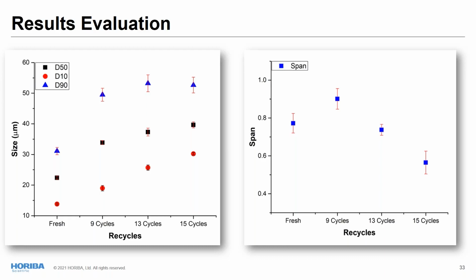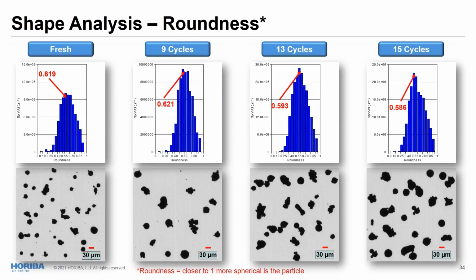It can be a good thing if, let's say, you're making a pharmaceutical ingredient or any other chemical where you want to control the speed of the chemical reaction. Of course, the narrower the particle size distribution, the more homogeneous the reaction is going to be. This is exactly what happens with airbag powders. But in the case of materials where you want to compact the material, you want a broader distribution so you can use the different sizes to fill the gaps between the particles. So when we look at the pictures we took of the particles, it is clear why this is happening.